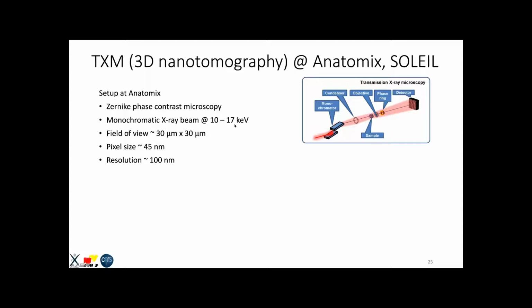So the experiments we did were at 10 to, well, they have the capability to do it at 10 to 17 keV. We did it at 10 keV, and we will do it again at 17 keV. They have a field of view of this detector at 30 by 30 microns with a pixel size of as little as 45 nanometers and a resolution as low as 100 nanometers.